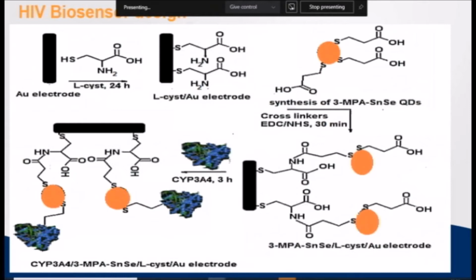L-cysteine has a thiol group, as you can see here. The thiol group has a high affinity for the gold electrode. So once we have this thiol group on the surface of the electrode, we have another group that is free for attachment of another layer.